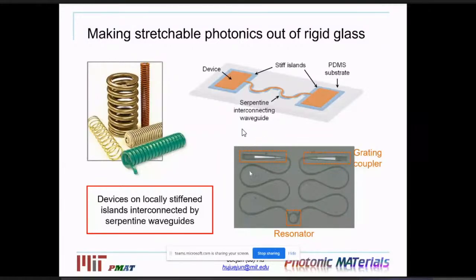Besides these serpentine waveguides, we also have some critical photonic components that we do not want any mechanical deformation on at all. Examples are grating couplers as well as resonators. When you stretch these components, you change, for example, the pitch of the gratings, and this changes the operation wavelengths of the devices. That's not desirable. So we also create locally stiff islands by patterning these devices on a stiff epoxy material. By doing so, we prevent any local deformation on these critical components. Then we link these components using the serpentine waveguides to create a photonic circuit.